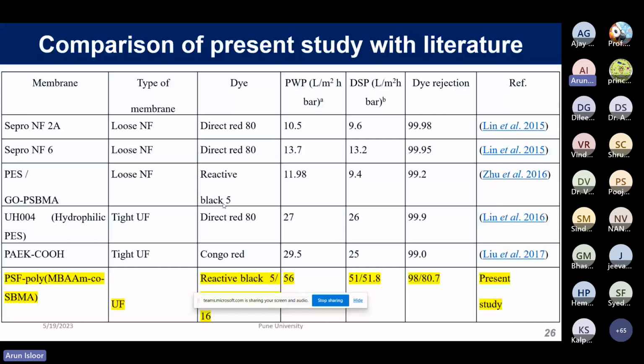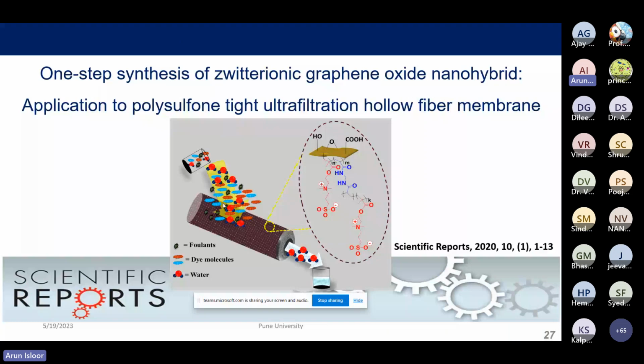Then the second one is the continuation of this one, with a slight modification, because as you know, many researchers across the globe are working on graphene oxide. And as I mentioned, we wanted to be something different from the regular graphene oxide type of work. Our applied strategy here was graphene oxide, which is known to improve the hydrophilic nature and give more mechanical stability to the membranes. And the zwitterionic polymer nanoparticles, which were fabricated in the previous one, can enhance the hydrophilicity and improve the anti-fouling nature. So we wanted to introduce both these properties together.